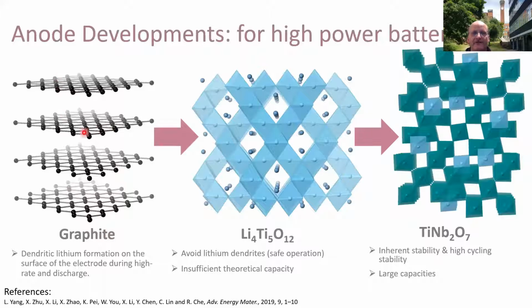So that's the conventional. Then if you want to go to rapid charge, you could use this lithium titanate material, which has the spinel structure. And this gives you safe operation at very rapid charge. However, the amount of lithium you can insert into this material is comparatively low for its weight. So it's relatively lower energy storage than the graphite.